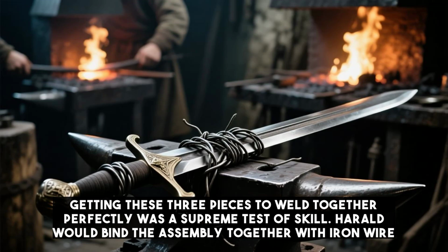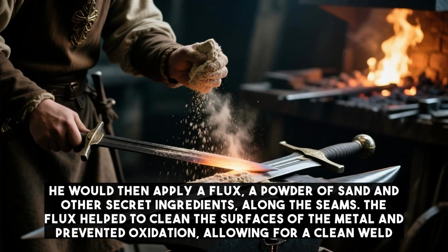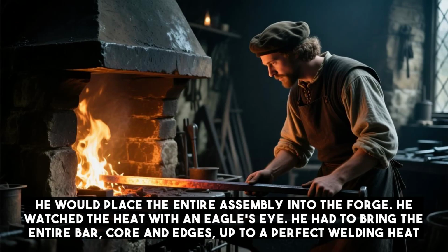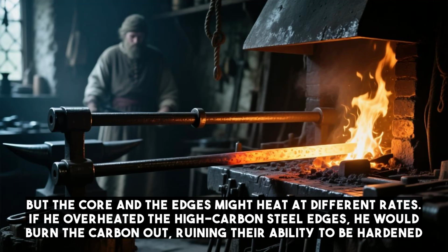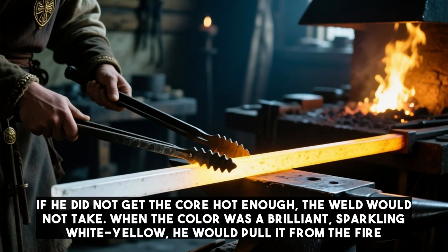Harald would bind the assembly together with iron wire. He would then apply a flux, a powder of sand and other secret ingredients, along the seams. The flux helped to clean the surfaces of the metal and prevented oxidation, allowing for a clean weld. He would place the entire assembly into the forge. He watched the heat with an eagle's eye. He had to bring the entire bar, core and edges, up to a perfect welding heat. But the core and the edges might heat at different rates. If he overheated the high carbon steel edges, he would burn the carbon out, ruining their ability to be hardened. If he did not get the core hot enough, the weld would not take.